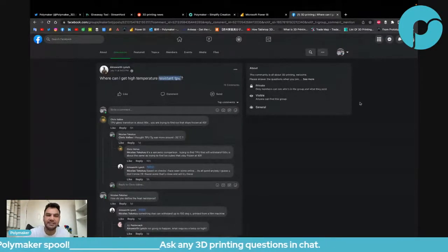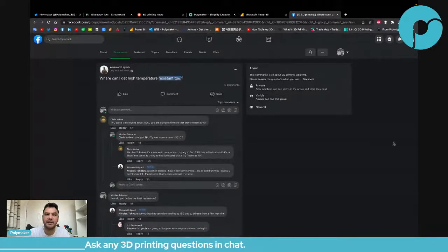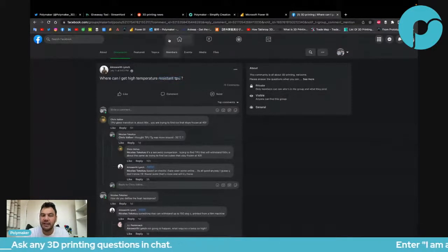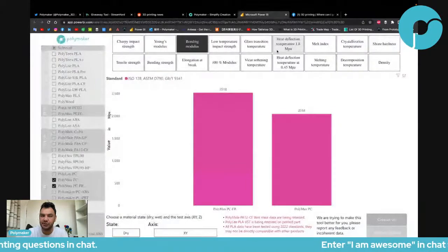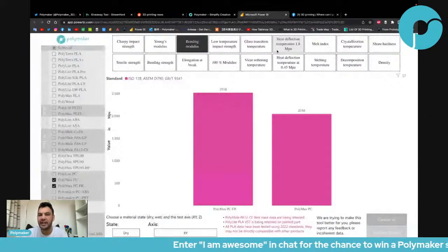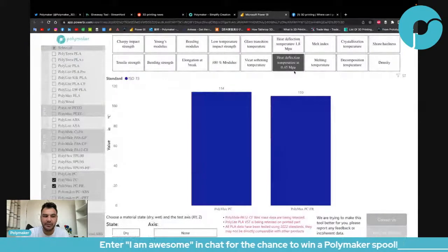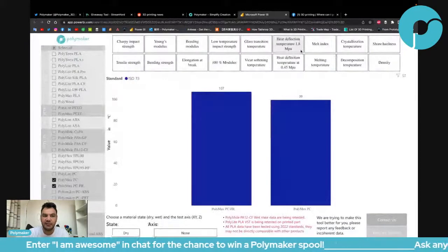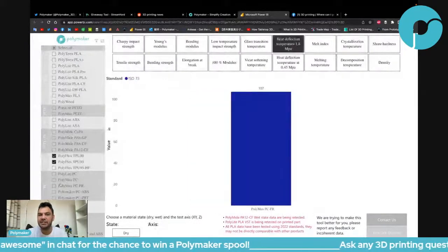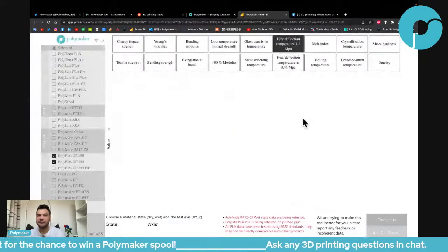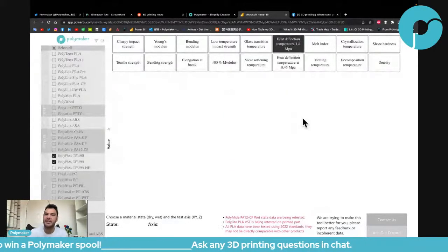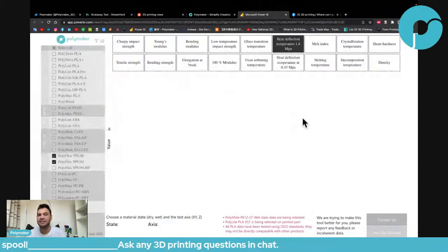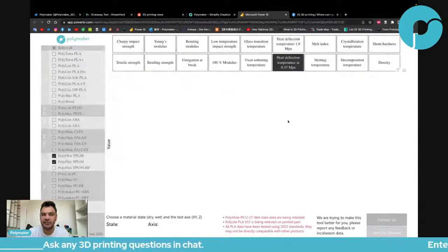The heat resistance has to be defined, and that's why here you have heat deflection temperature at 0.45 megapascal, heat deflection temperature at 1.8 megapascal, and TPU doesn't have this. You see, if I select my TPU, there is no HDT. Why is there no HDT? Because even at room temperature, it cannot resist that stress.